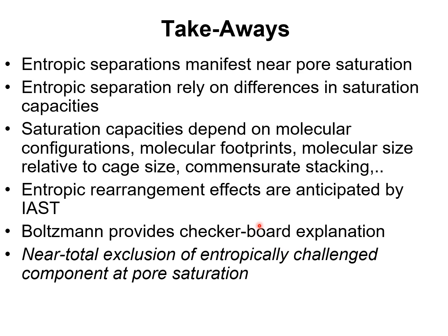And one important characteristic of entropic separations is that we have near total exclusion of the entropically challenged component at pore saturation. And in this presentation, we have used the simple Boltzmann expression, S is equal to k ln W, in order to explain and elucidate entropy effects using a checkerboard analog of adsorption sites within the pore topology.